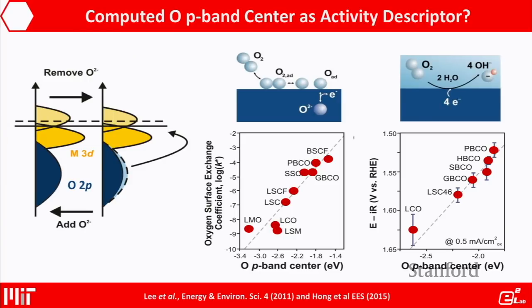As you can see from these two plots, for the oxygen surface exchange kinetics, which is the reaction exchange between O2 and O2 minus, if you make the compound more covalent, going from left to right, you can increase the exchange kinetics by 6 orders of magnitude. Similarly, if you increase the covalency for oxygen evolution in basic solution, you can also increase catalytic activity by 2 orders of magnitude. So this is a correlation between measured catalytic activity, in different environments for oxygen evolution, versus a computed oxygen p-band center.